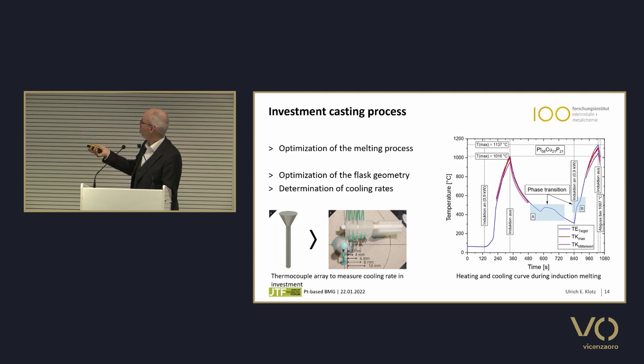We have different temperatures plotted here. The blue line is the crucible temperature, the red curve is the maximum temperature, and the pink curve is the average temperature of the melt. So we go up to 1,000 degrees. Then you see nothing happens, normal cooling, and then we have a certain undercooling, and then the crystallization occurs during cooling. And then when we heat the material again, we see the melting occurs.